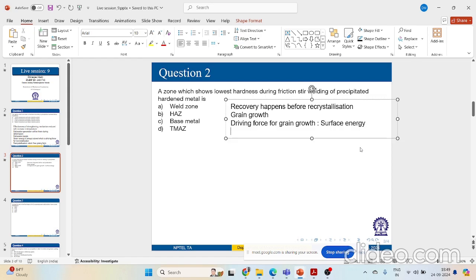And why will these variations in the structure and hardness of the heat affected zone occur? Because you will be experiencing different thermal cycles during your welding or joining, different temperatures at different locations. The zone close to your fusion boundary will experience higher peak temperature for longer time, which will cause more severe recovery, recrystallization, and grain growth phenomena. While if you are moving away from your fusion boundary, or the nugget, and going towards the base metal zone, both peak temperature and retention period will decrease, and that will cause lesser recovery, recrystallization, and grain growth phenomena. As simple as that, right?